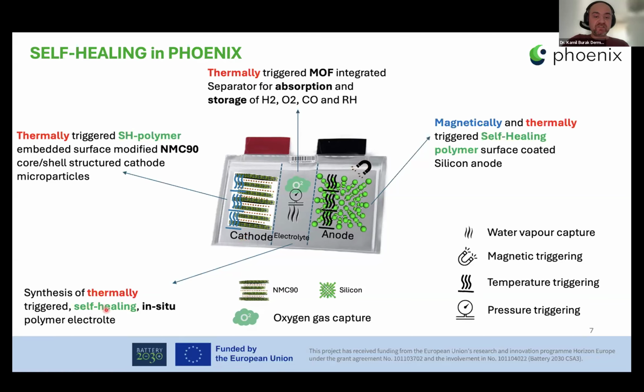We also have the thermally triggered self-healing in situ polymer electrolyte, which has been placed in the cell. And we also have thermally triggered metal organic frameworks, MOFs, and MOF integrated separators for gas absorption, namely hydrogen, oxygen, and CO, and humidity. And on the anode side, we have the magnetically and thermally triggered self-healing polymer surface coated by silicon anode.